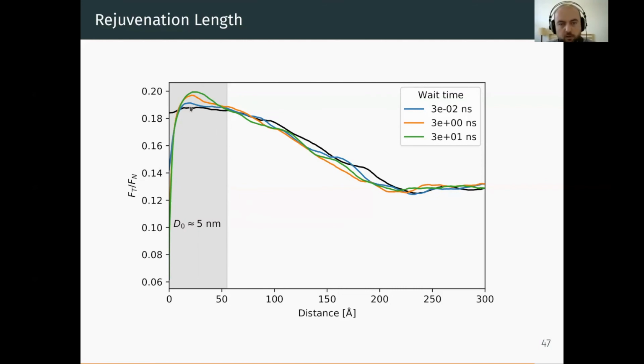And what I also measure from those simulations is the magnitude of the increase of the overshoot. And I also see, just like in the experiment, a logarithmic aging in the friction force. So this is still work in progress. And as you can see, the waiting times here are in the scale of nanoseconds because I'm using molecular dynamics. Time scales of seconds are unfortunately not currently possible. So this isn't a full story, but I think it's a very nice springboard towards understanding the nanoscale friction mechanisms of those fatty acid molecules. So hopefully this convinces you that atomistic modeling is very relevant for tribology.